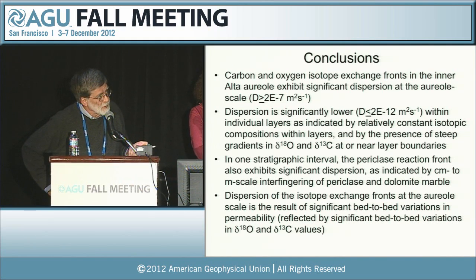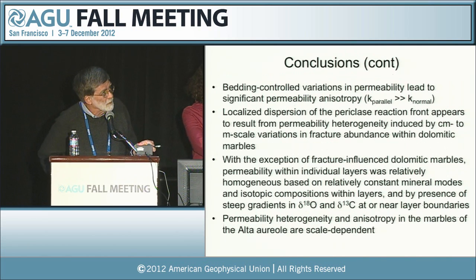aureole scale, and in contrast, that dispersion is significantly lower at the individual bedding layer scale, as indicated by relatively constant compositions of the materials within the layers and the presence of these steep coherent gradients at the layer boundaries. I'll skip this one. The dispersion of the isotopic exchange fronts at the aureole scale, we think, is the result of significant bed-to-bed variations in permeability, reflected by significant bed-to-bed variations in the oxygen and carbon isotopic compositions.